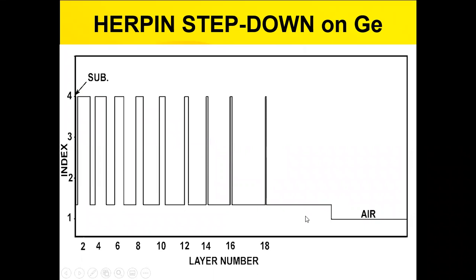However, as I've showed in my book also, whatever your lowest index you have available to you is going to limit how good you can do in terms of the lowest average reflectance in a very broad wavelength band. The bottom line is it'll end up looking like you have transformed a high index substrate into a low index substrate of whatever your lowest index is.